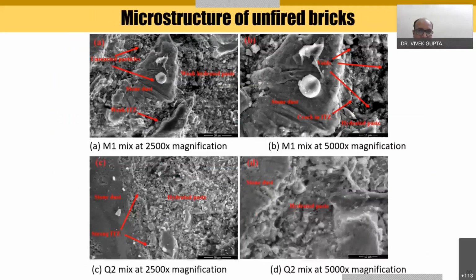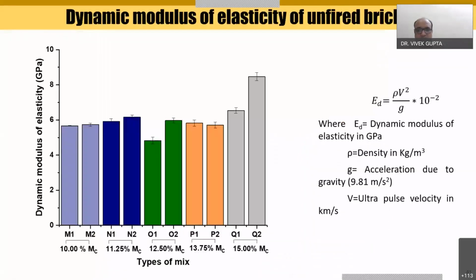Then this is the microstructure we have observed, like in the M1 mix as compared to the Q2 mix. In the Q2 mix you can see we observed the strong ITZ, the interfacial transition zone, whereas in the M1 mix we found the weak hydrated phase. So the results observed in the macro test, like the compressive strength test results, are in good relation with the microstructure observed in the unfired bricks.